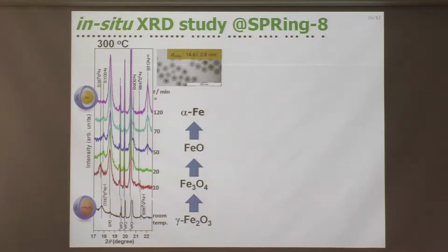Let me briefly explain the reduction processes. In order to study them, we carried out in-situ XRD measurement. Here shows the results from the smaller samples. I will skip the details, but the starting gamma iron oxide was reduced to Fe3O4, then FeO, and finally to alpha iron.